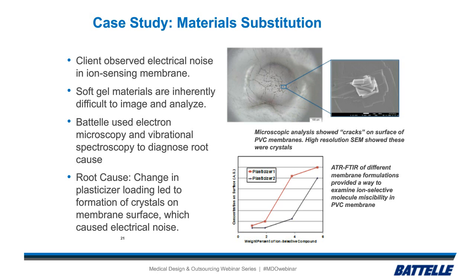And the second thing was the plasticizer, the PVC card that the microchannels are molded into had a different plasticizer than the original PVC. And that plasticizer also played part of the role here, that when it leached into the hydrogel, it caused this supersaturation, nucleation, and crystal growth that came out. So this was, again, a very complicated system of things going wrong. It wasn't just one thing. It was a number of things that all came together at the same time.